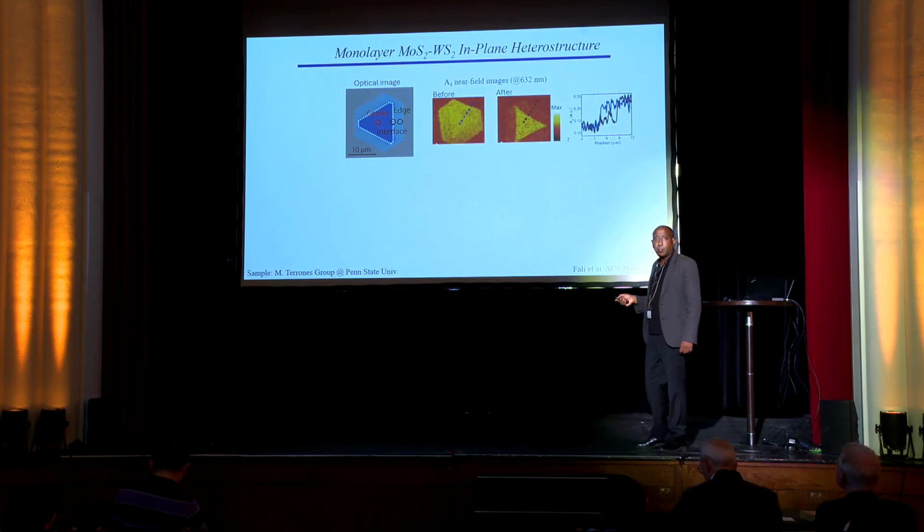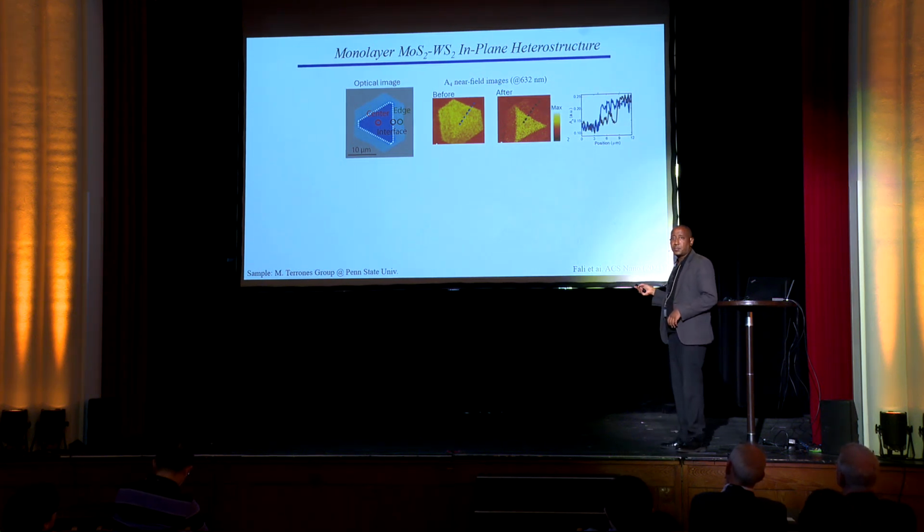What we noticed, among other things, was that if you expose this kind of monolayer to light, photons extensively, you would see the outer layer completely degrades within some time frame, and you would end up with only the inner being stable.